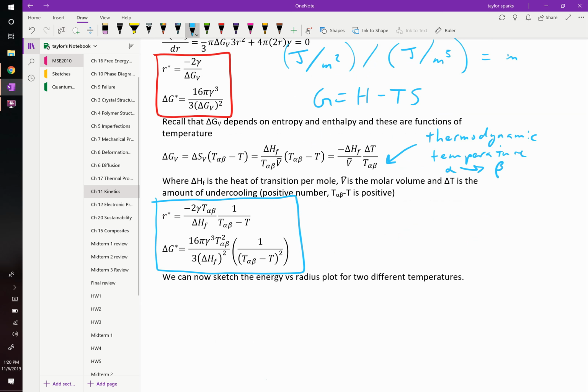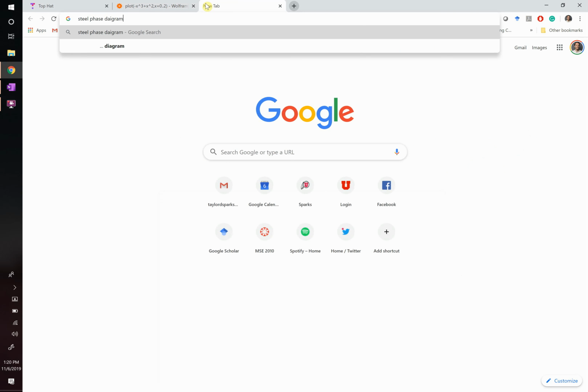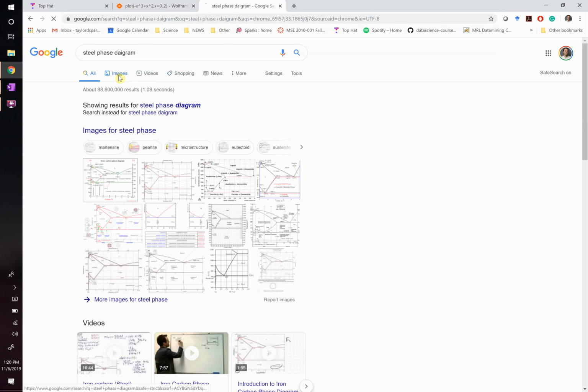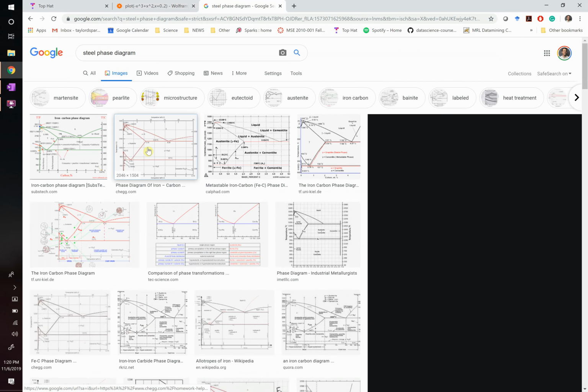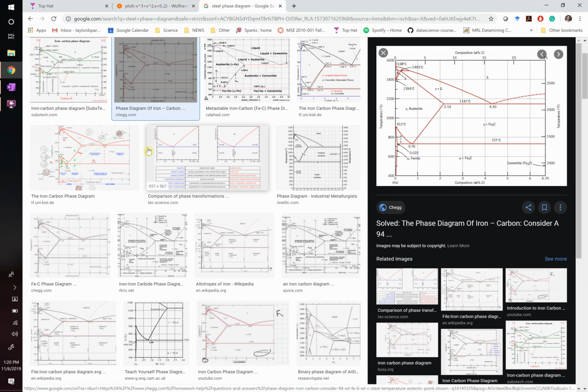Why do they do all that? Why all those substitutions? The reason is because a phase diagram can tell you where this should happen: T alpha beta, whatever transition you care about. Let's do steel for a minute. If we look up the steel phase diagram, remember, everything on this diagram is assuming equilibrium. So if you are at, let's say, this gray line, that's your composition. That right there is the temperature at which you should start to go from pure austenite, gamma, to a mixture of austenite and Fe3C. That is your T alpha beta at that point.